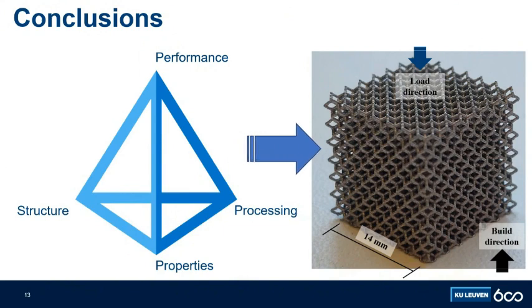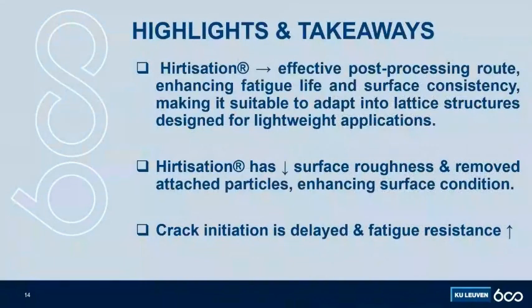For the conclusions, we can think of the analogy of the materials tetrahedron, where structure, properties, and processing act synergistically together to enhance the final performance of the material. In this case, the processing is the hirtisation, and the final goal that was achieved was the increase in the fatigue lifetime. So the main highlights and takeaways are that hirtisation is indeed an effective post-processing route, enhancing fatigue life and surface consistency, making it suitable to adapt into lattice structures designed for lightweight applications.